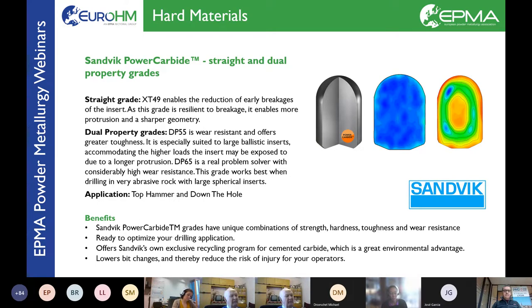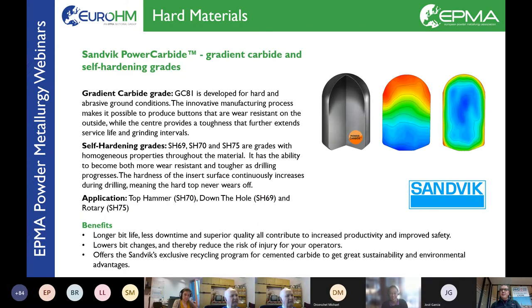I don't know, Kenan, will the next ones come right after? Yes, so there are two more grades in this family. And the top one is called the gradient cemented carbide, because it is a gradient cemented carbide. In this case, it's a dual phase material from the core to the outer part, in comparison to the dual property we had earlier. In this case, it is in the two-phase region of tungsten carbide and cobalt from the